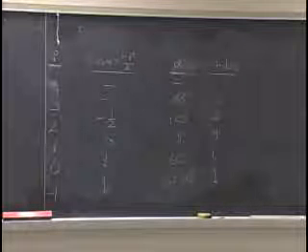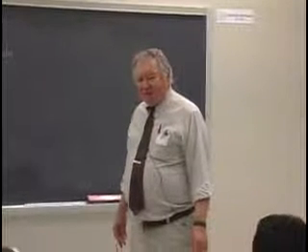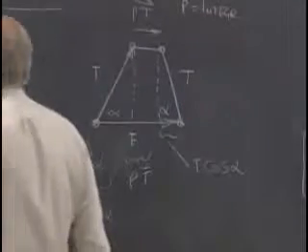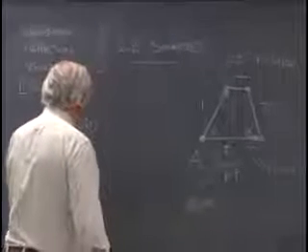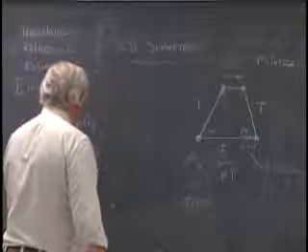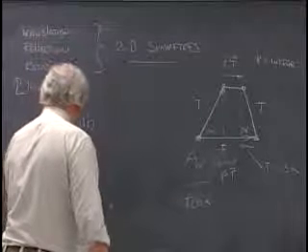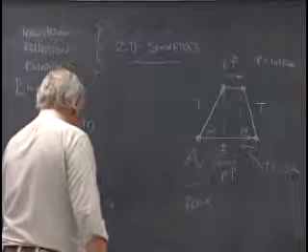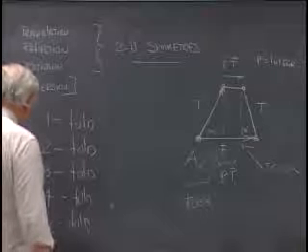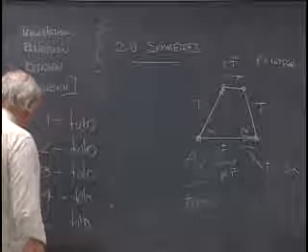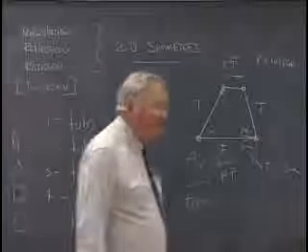So this is a momentous result. We've shown that if you are going to have a pattern that has a repetition by translation in it, the number of rotational symmetries that can be added are either no symmetry at all, a 2-fold rotational symmetry, 3-fold, 4-fold, or 6-fold. In other words, the axis: no symmetry at all, 2-fold, 3-fold, 4-fold, or 6-fold. Nothing else.